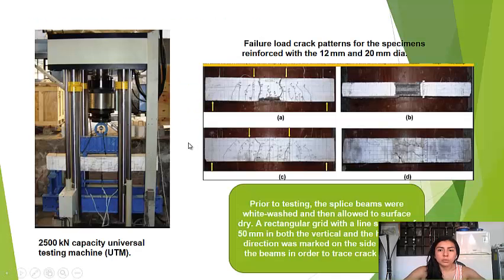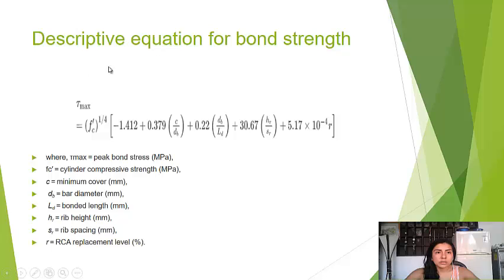Test setup. The specimens were tested using a universal testing machine with a capacity of 2,500 kilonewtons. As a result of this test, the cracking behavior was fundamentally similar across all the specimens. Descriptive equation for bond strength. Finally, as a result, a power equation provides the best representation of the effect on the resistance of recycled aggregate concrete.